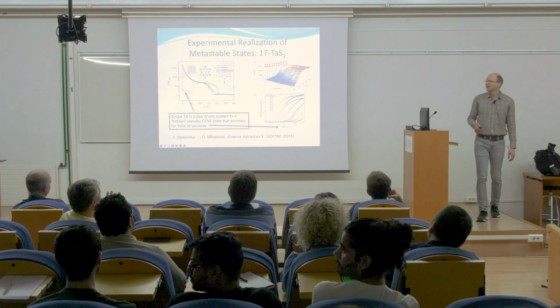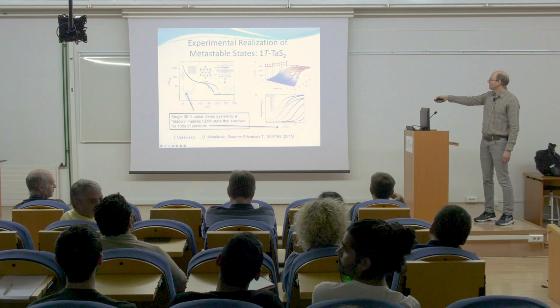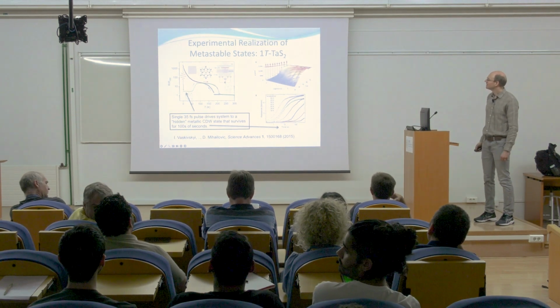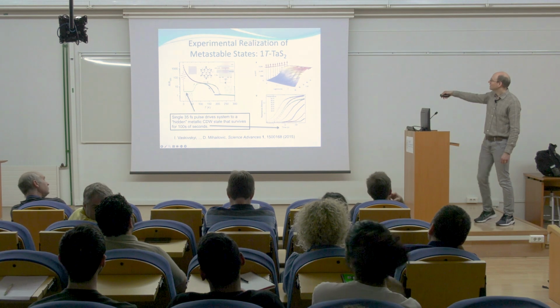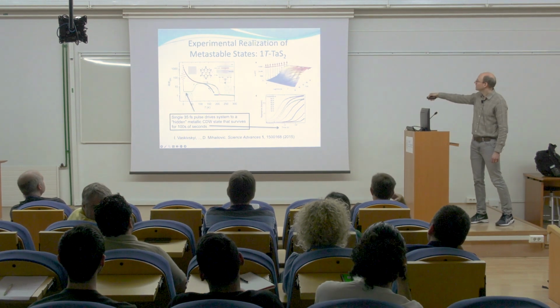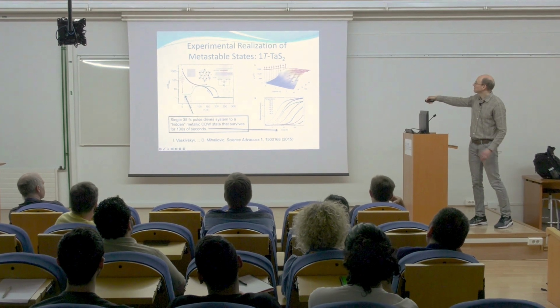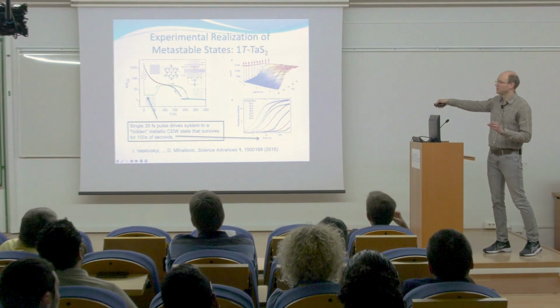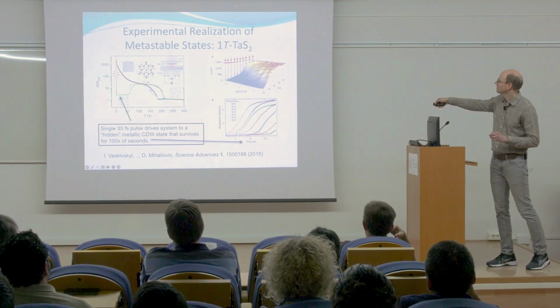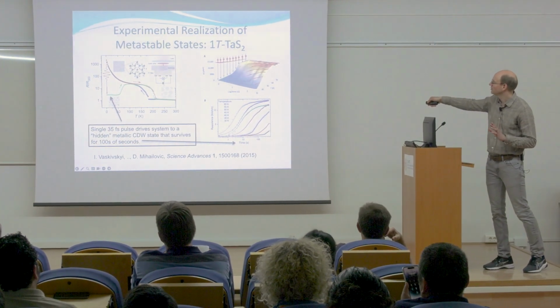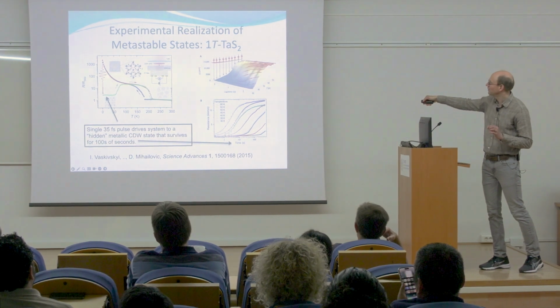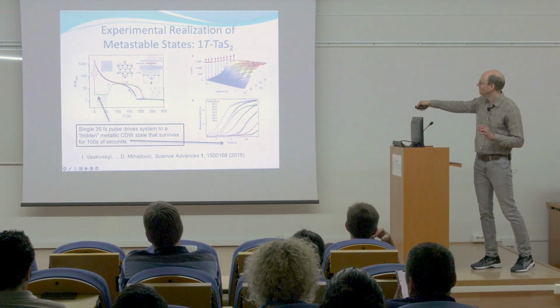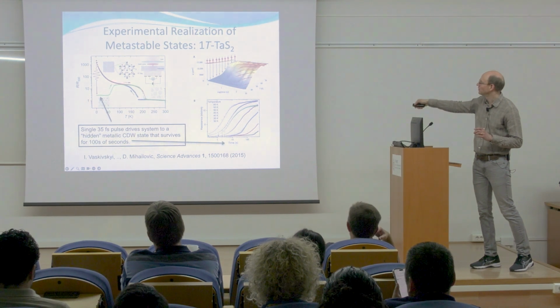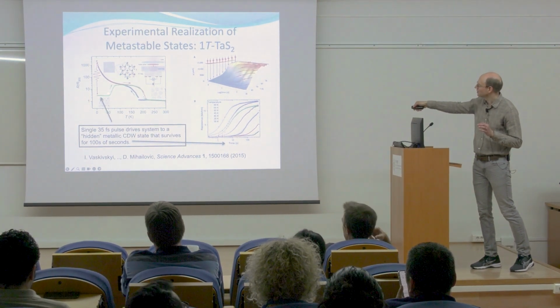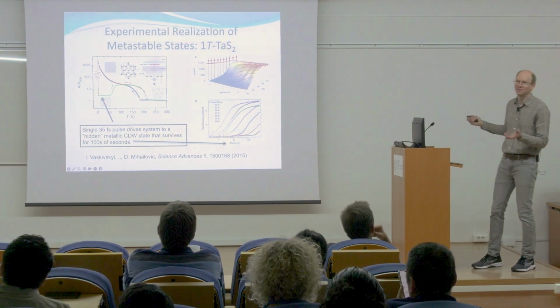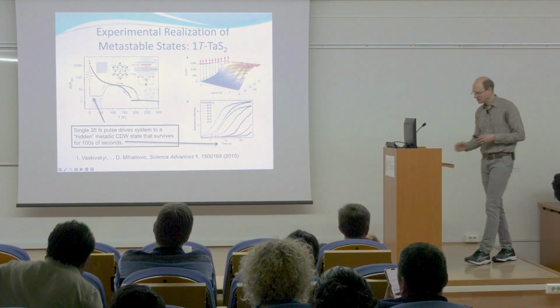The hysteresis-like behavior between 170... is that in the presence of the pulse or independently of the presence of the pulse? Right, so what's shown here is the blue and the red are with no pulse. If you lower the temperature with no pulse, then you'll follow this blue curve. And then if you heat up again, then you'll come this way and follow the red curve. The green is what you get when you follow the blue, hit it with light, which brings you to the green, and then you return via the green. Okay, any other questions?